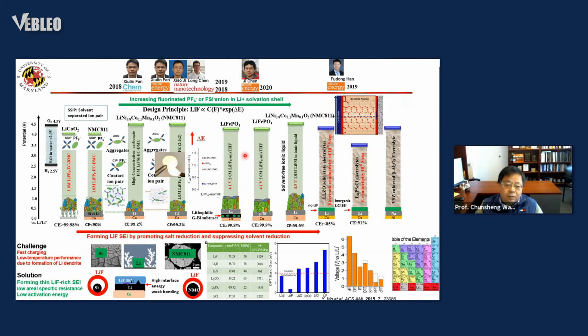And we know we can use the anti-solvent. Anti-solvent is not an ionic conductor because it does not dissolve salt, but it can help localize the high concentration. And for beta alumina in the sodium ion battery, we also use the same idea. We use a non-sodium-ion-conducting phase to stabilize beta alumina, because this is not a sodium ion conductor. So it is mechanically strong, and when attacked by sodium, it can form a really inert pathway. So it makes the whole electrolyte mechanically strong.